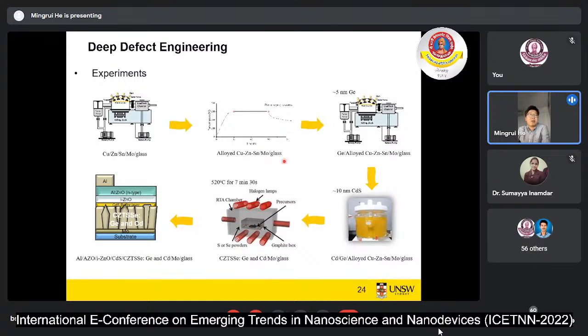This process will enable the precursor to become alloyed phases. Before, it was just a stack order. After that, I put a thin germanium layer in here as a germanium source, by sputter as well. Then I deposited cadmium sulfide as a source of cadmium, around 10 nanometers. So here is the structure of my precursor.